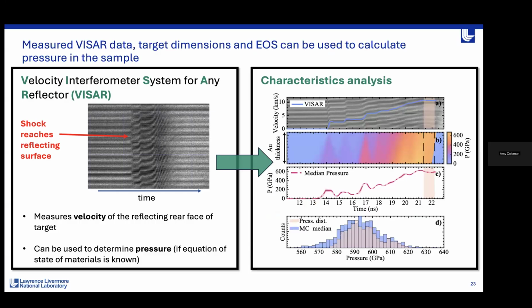Now, from that velocity, it's a bit of a step to get to pressure. The way that we do this is by a method called characteristics analysis. So the pressure at the probe time during our experiment is determined using this sort of one-dimensional characteristics analysis, and our VISAR data here serves as a boundary condition. The inputs for the characteristics analysis are things like the VISAR, the measured target metrology, so the thickness of the layers of our target package, and also tabulated equations of state for the materials in the target package.